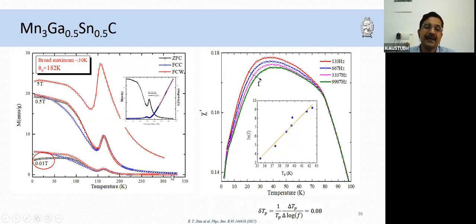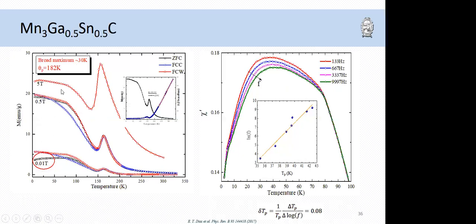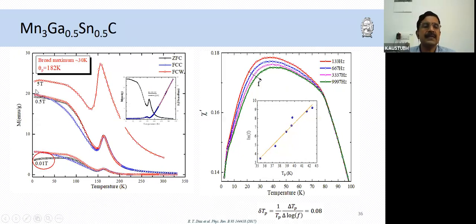And you can see that from the paramagnetic state, suddenly the magnetization increases very strongly. And then suddenly, as if there is an antiferromagnetic transition here, and then it again increases back, which is seen in all fields from 0.01 Tesla to 5 Tesla. And we were also perturbed by this broad feature here, which showed a bifurcation between field cooled and zero field cooled, and with field that bifurcation decreased. And it's as if there was some sort of a glassy transition.